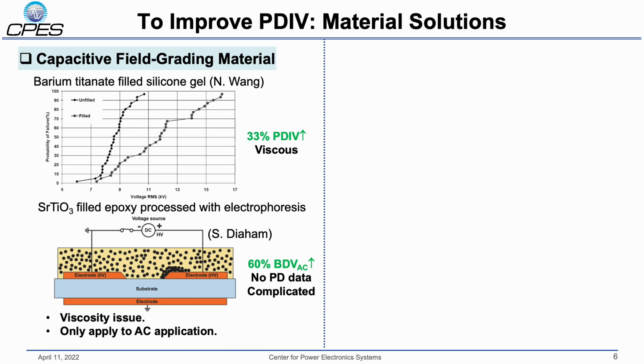In this work, strontium titanate was filled in the epoxy, and to increase the packing density in the critical regions, electrophoresis was used to redistribute the fillers after the encapsulant curing. They were able to increase the AC breakdown voltage by about 60%.